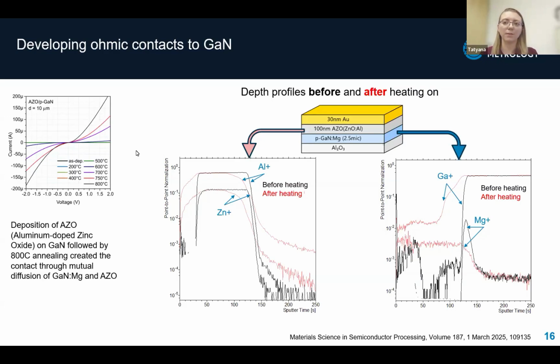On the left, you can see the IV curves, which show how the contact properties evolve with temperature. Moving to the depth profiles, we compare the sample before in black and after heating in red. The left graph shows that aluminum and zinc ions from the AZO layer diffused into gallium nitride after heating. The right graph shows the opposite: gallium and magnesium ions from gallium nitride diffused into the aluminum zinc oxide layer. And why is this important? Because this mutual diffusion is key to forming a reliable electrical contact. Even though ToF-SIMS gives us semi-quantitative data in this case, the trends we see here are trustworthy and meaningful.